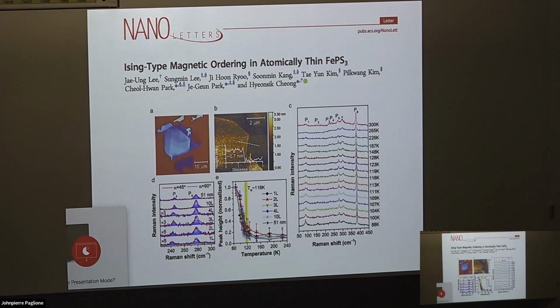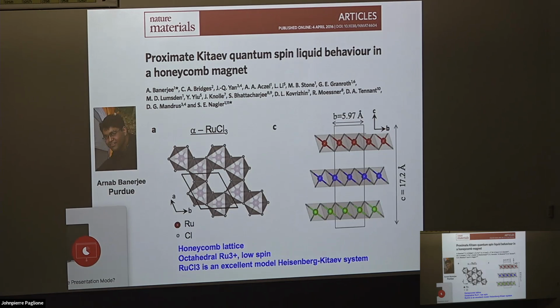Here's an antiferromagnet. Also interesting. It's another set of materials, like a transition metal phosphorus trisulfide. Those are also quite common. So here's one that we've worked on, ruthenium trichloride. This one is close to a Kitaev quantum spin liquid. It's not exactly there, but it's quite close. It has very strong Kitaev interactions. But it's also a highly cleavable material. And Arnab, I don't know if you guys know Arnab, but he's at Purdue now. He was a postdoc at Oak Ridge when he did a lot of this work. So this one cleaves pretty nicely, and actually it's relatively stable in air.